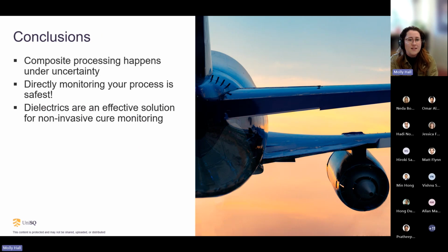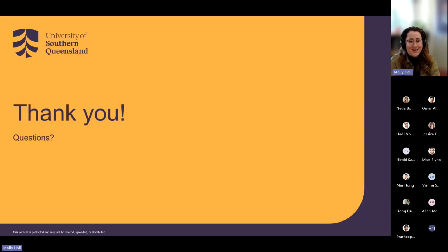So just to conclude, composite processing happens under uncertainty, and it's always good to capture what that uncertainty is. If you can't, then directly monitoring your cure process is really the best way of going. And dielectrics, I think, are a very effective solution for this, especially for aerospace, because there are some non-invasive solutions. And that's what I have.